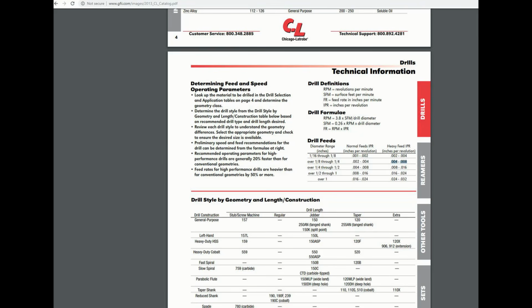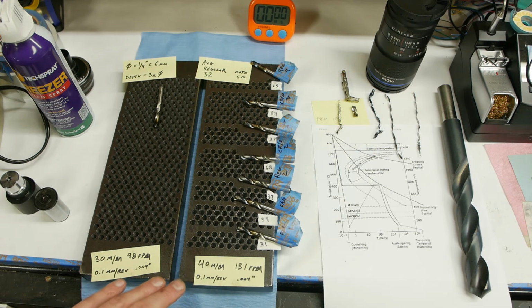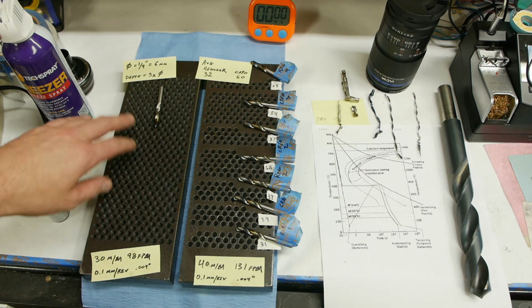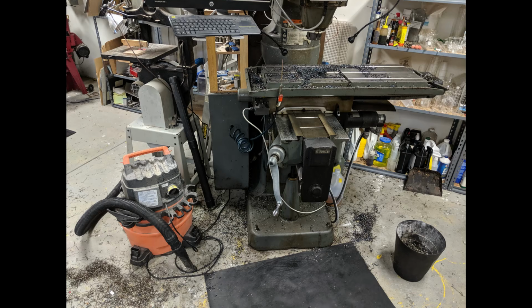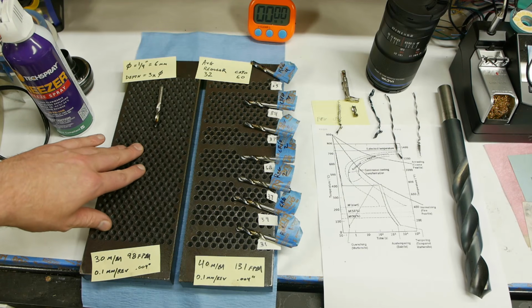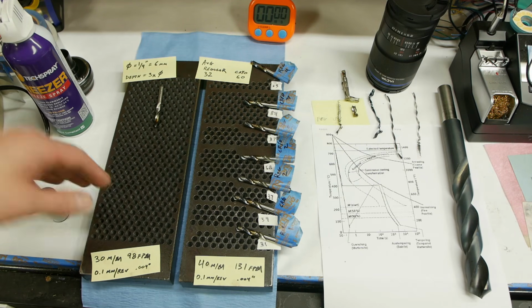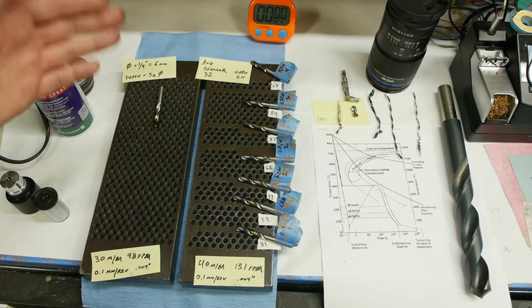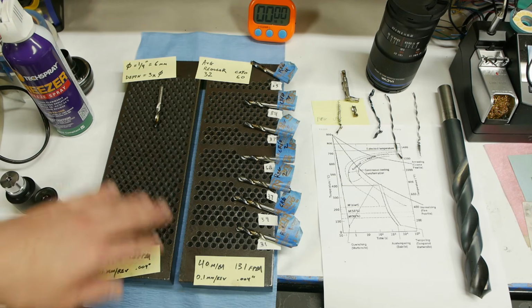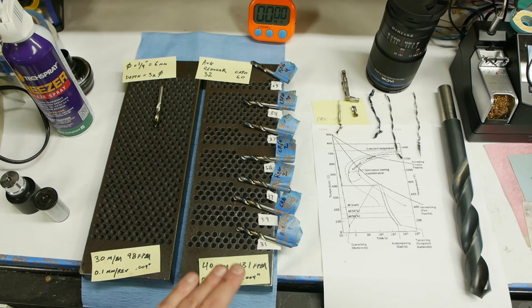But I actually got all of these holes out of this single bit, and it was still cutting at the end. So the trick is that the surface speed makes a big difference, and I just can't test a more normal surface speed because I don't have as much steel to go through. So if I were to test this one with cryo and regular, I would need a 4x8 foot sheet of steel to test all this out. So anyway, I went to a much more aggressive machining setup so that the bits would in fact fail faster.